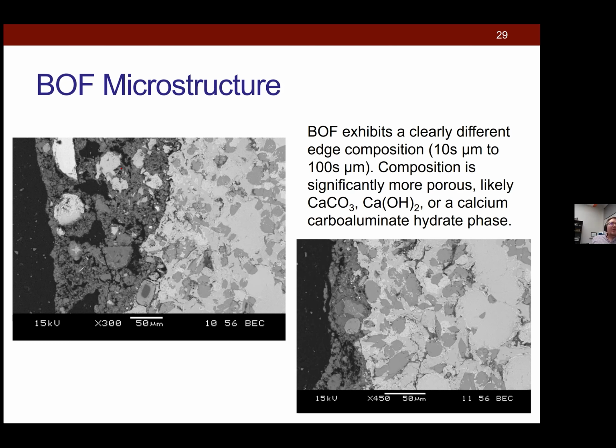So somehow on the surface of this aggregate, we are getting a bulk change in microstructure. We almost have the hard interior of the slag aggregate, and then this sort of ITZ, you can think of it, a weak zone, and then it bonds to your cement paste, where there's going to be another ITZ.